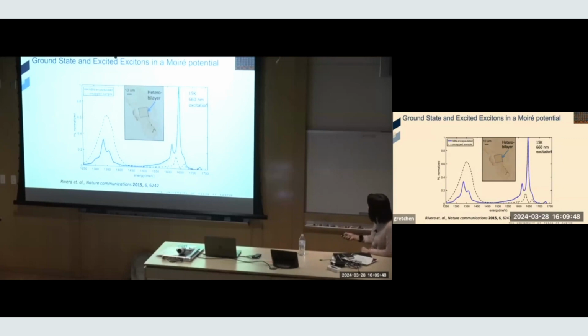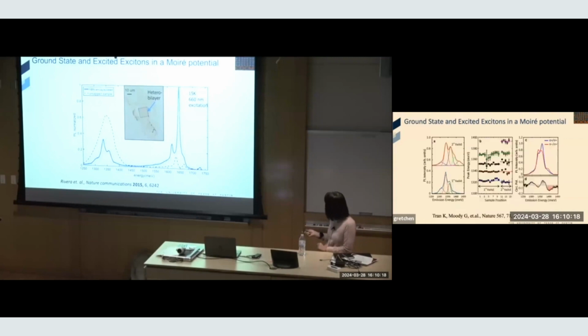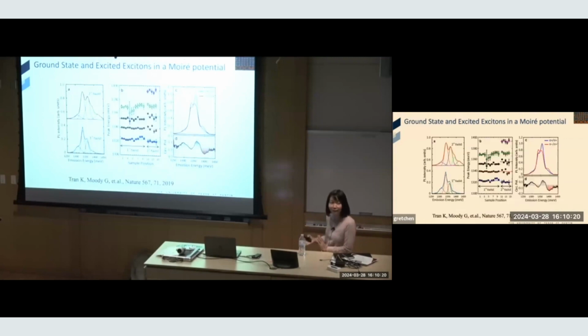But another thing that people learn is to actually encapsulate them in hBN. hBN is this high gap insulator with 6 eV gap. They're transparent. The samples are ugly if you exfoliate and stack them. So this is where they are. And then we had this result for a couple of years. We don't know what they are. We thought maybe they're bubbles, that maybe samples are just inhomogeneous. And that it takes very dedicated students to make a dozen of them. And then we slowly began to notice some trend.